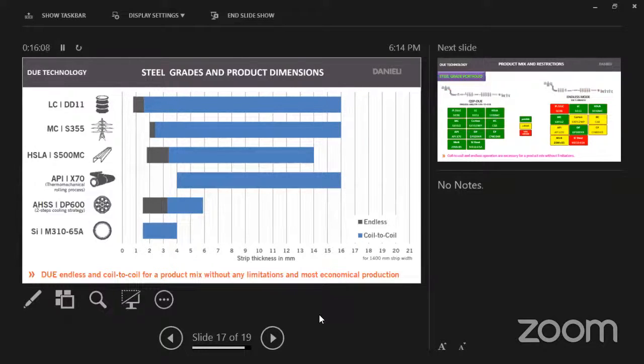And if you go for the API grade, that means the 1:5 thumb rule ratio for producing the API grade, that means 140 divided by 5, it is around 28 millimeter. I can easily produce nowadays from 140 millimeter slab thickness the actual API grade, X70 grade, 28 millimeter.